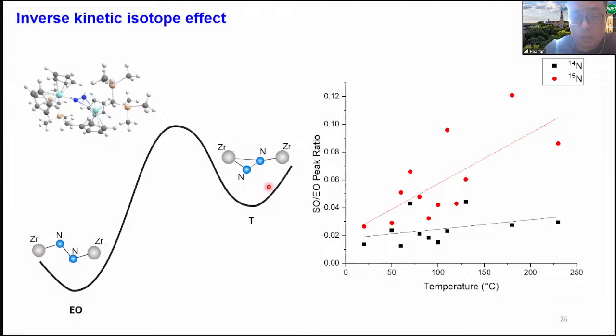In this case, the product here is the triangular structure with 3 zirconium-nitrogen bonds, whereas my starting structure, the end-on structure, has 2 zirconium-nitrogen bonds. So replacing N14 with N15 would decrease the zero-point energy of the transition state more than it does the starting structure, the end-on, and therefore we expect the N15 structure to have a lower barrier than the N14.